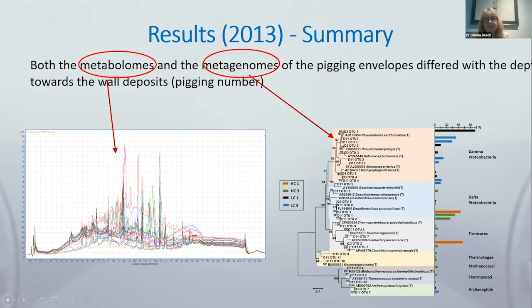Then I will skip a few slides, because what happened is that both metabolomes and metagenomes of the pigging envelopes showed us that populations differ depending on the depth of sampling. The population very close to the surface of the pipe was very different, and the metabolome associated with this population was very different from the metabolome collected from the very first pig, the one closest to the bulk fluid. What is very important is that when people sample from these systems, they tend to take a sample and homogenize it. Then all the information is lost, because one doesn't really know what kind of metabolomic situation and what kind of population is really responsible for the corrosion one sees in the systems.